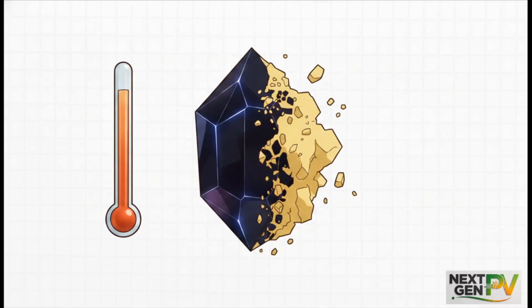lead. So researchers pivoted. They swapped out the methylammonium for formamidinium, creating FAPbI₃. This gave us a better band gap and even higher efficiency. But it introduced a fatal flaw, known as the FAPbI₃ problem. At room temperature, pure FAPbI₃ is highly unstable. The atoms actually rearrange themselves into a non-photoactive yellow phase, where it basically just stops absorbing light altogether. Not exactly what you want in a solar panel.